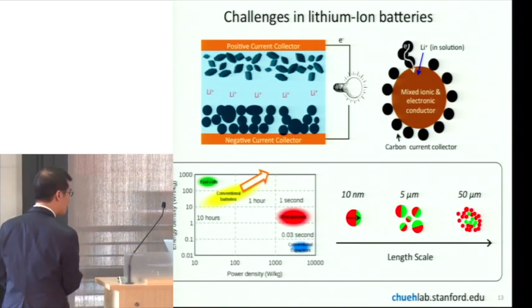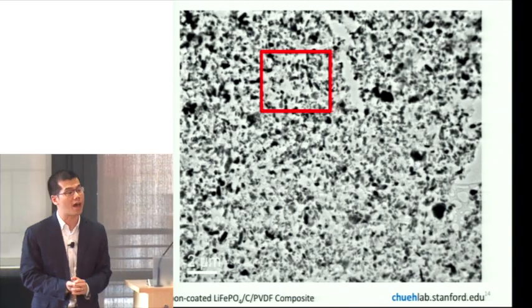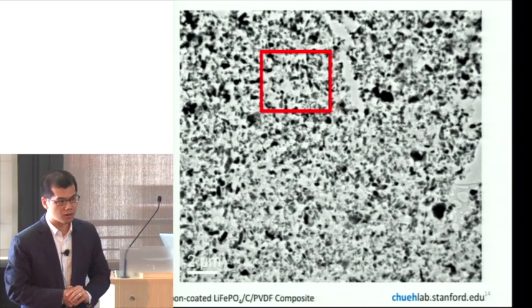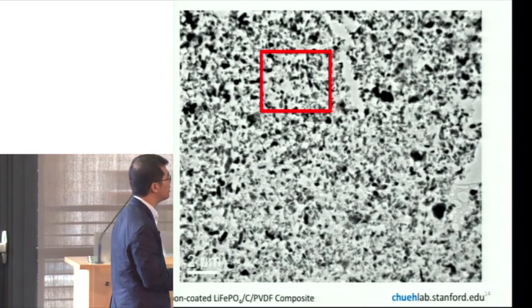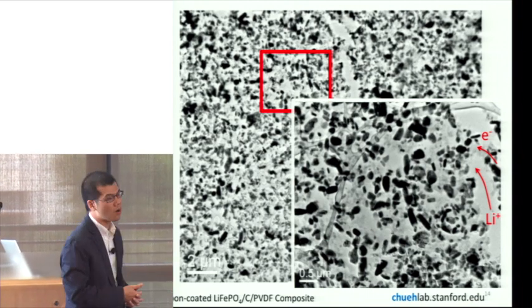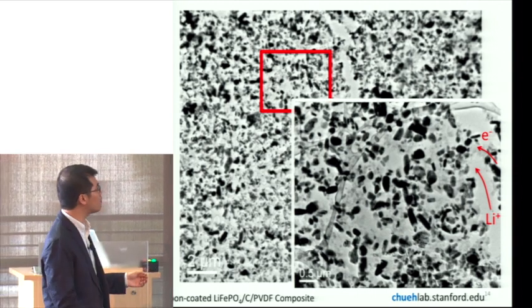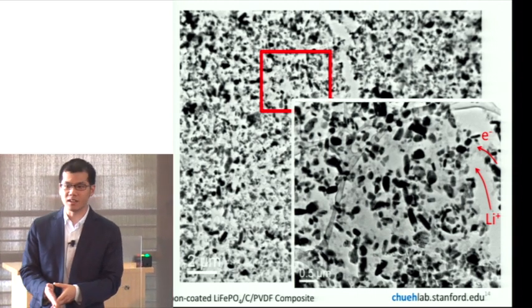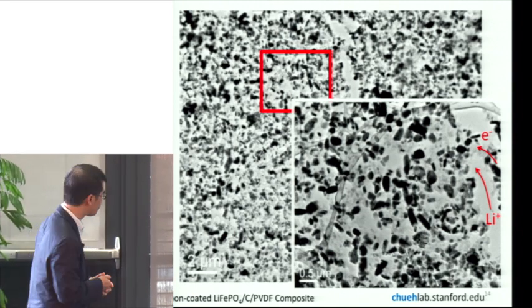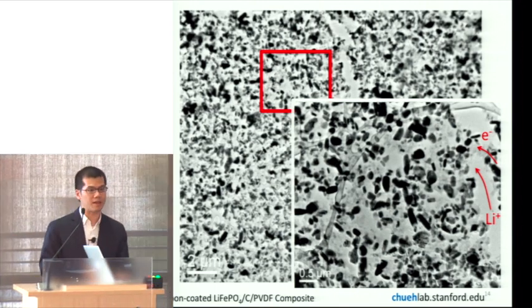What makes it really hard to optimize batteries is that it is not a simple AA cell. It is a very multi-scale problem ranging from a single nanoparticle on the order of tens of nanometers all the way up to hundreds and thousands of microns. Here is a real image: a cross-section taken from a commercial battery. You can see it's nothing like the schematic — it has funny-shaped particles, a distribution of sizes and shapes, and even discontinuities between particles and the pores between them, through which lithium and electrons must travel to store energy.